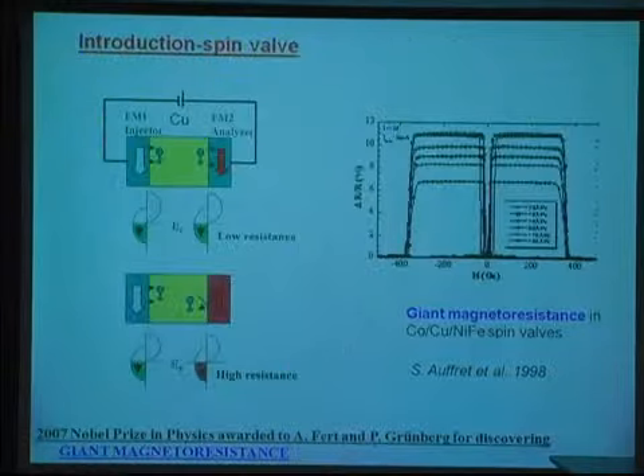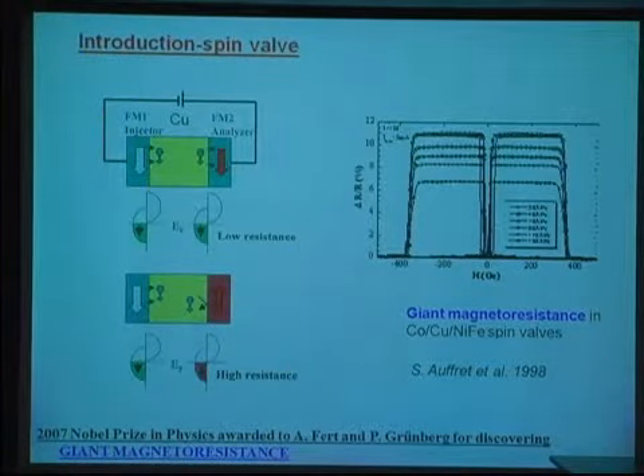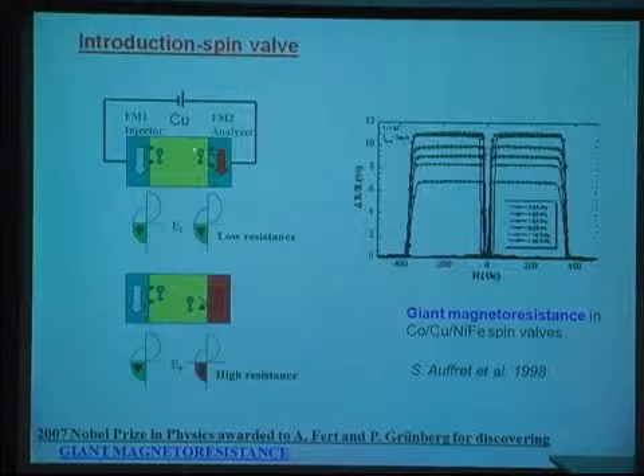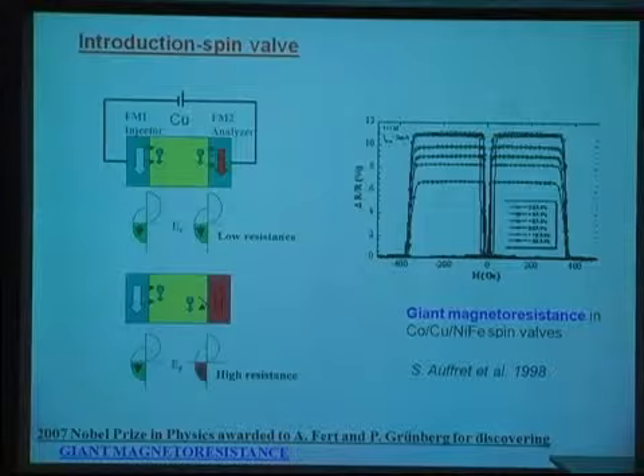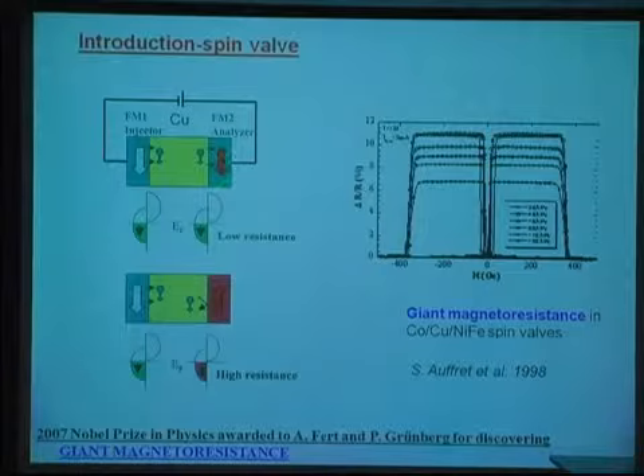Okay, so I would like to give you two examples of spin valve structure. So in the first example, the spacer is copper. In one electrode, I inject spin down electrons into the copper. And this spin-aligned carrier moves to the other electrode under the effect of the electric field. And then at the second electrode, there are two possibilities. The first possibility is that we have a large density of states for the spin down, so the second electrode can accept this spin, which means the resistance of the device is low.